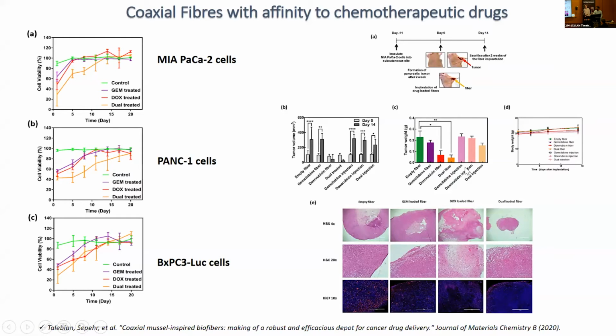And what we've also done was use an equivalent dosage of the drugs that was in the fibers, and we systemically injected them to see the difference between this local delivery and normal systemic delivery. And what we observed was that the local delivery had a significant reduction in tumor size compared to the systemic injection of drugs, which basically satisfied what we were trying to achieve.